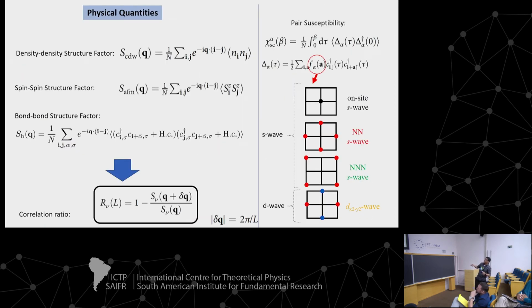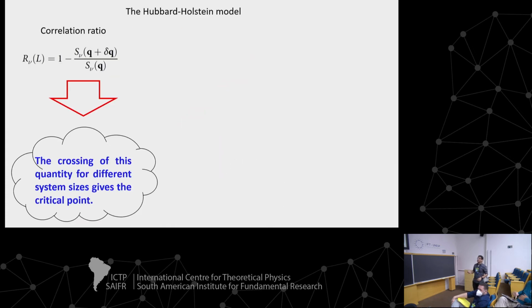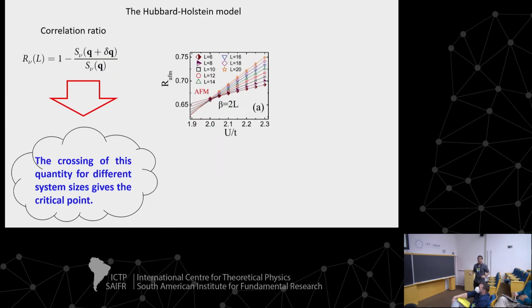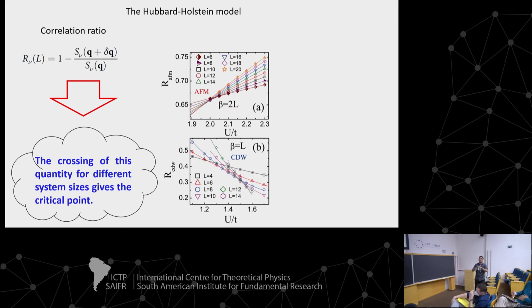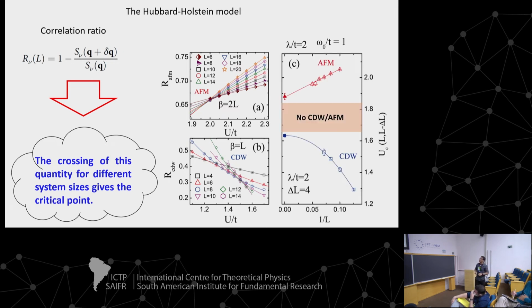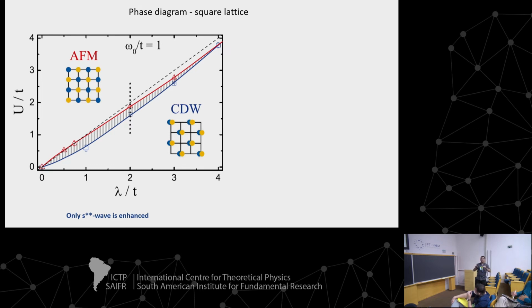We have analyzed many different types of wave symmetries. And in this case, the one that we have noticed that's the dominant one is this S wave, but it's not on-site S wave because of the Hubbard interactions. It's a nearest neighbor S wave symmetry. This is called S star wave. Yes, half filling, yes. Because away from half filling is horrible because of the sign problem, yes. Here we still have sign problem, but we can deal with it.